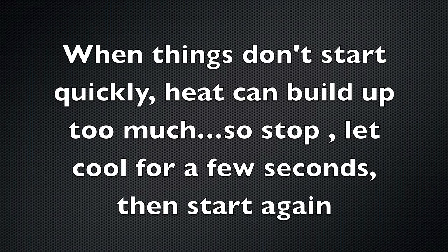Like I was on the end right there, and it took me an extra second to get the two to join. Instead of just keeping going, I just stopped, let it cool for 30 seconds or so, and then lit up again, and then things go a lot better. Because once that heat builds up, even if it's on the end, it's hard to outrun it. So if you have to hesitate at all, just stop and let it cool.